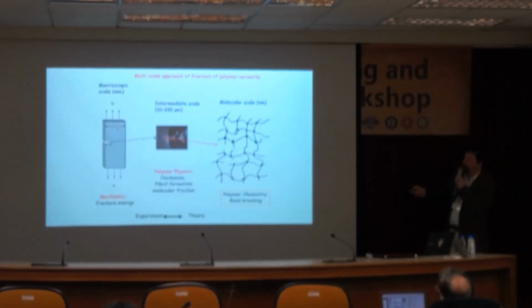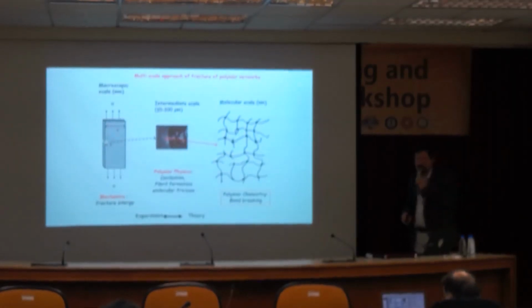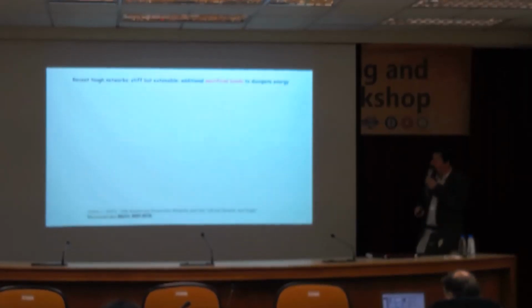So if we're looking at the length scaling here, and this answers part of the question, we have a macroscopic scale, which is the sample size, where you have your crack. Then, if you look at this crack tip, which is indeed fairly rounded, you have an intermediate scale, 10 to 100 microns, generally for these soft materials. This is really where polymer physics is important, where you have damage mechanisms like cavitation, formation of filaments, as you could see from there, and molecular friction. Then if you magnify again, you get the molecular scale, because these materials are actually polymer networks, so they're soft, flexible chains that are connected with cross-linking points. We would like to understand how breaking this, and this is really just a cartoon, affects this, and then eventually the macroscopic scale. So it's a hard problem. Even though it's nothing like the complexity of living things, for this type of material, it's not easy to understand.